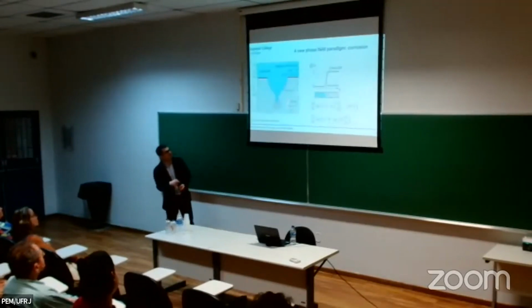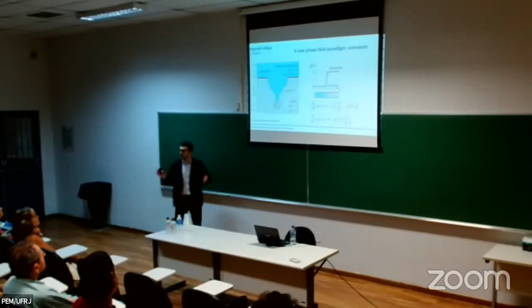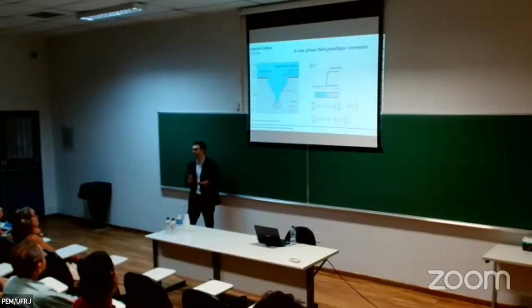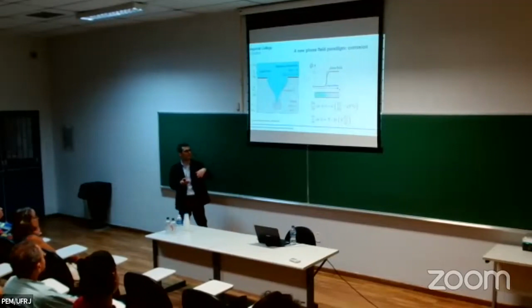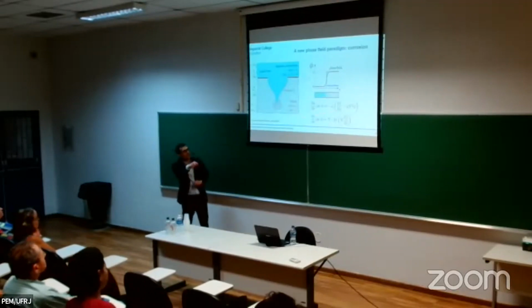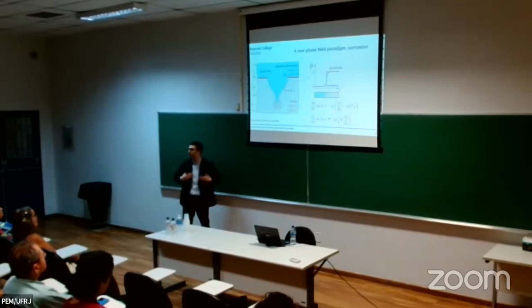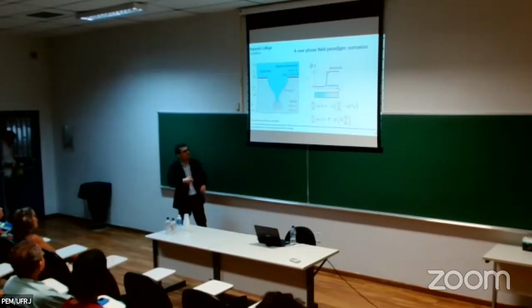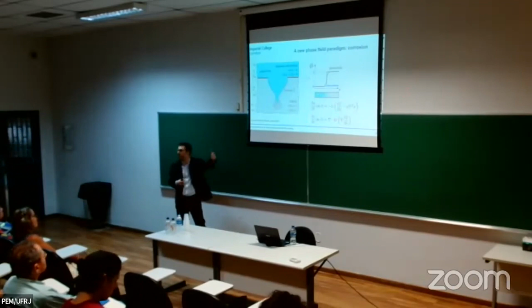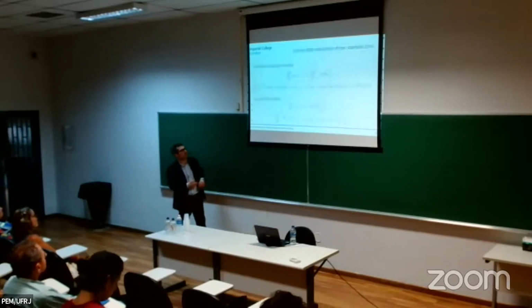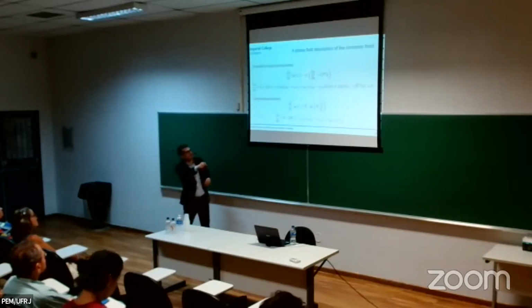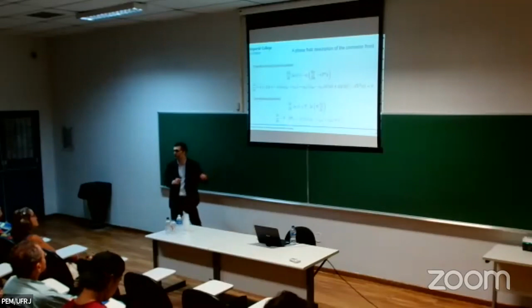We decided, okay, let's use phase field now to describe the interface between seawater and the metal. I won't get into the details for the sake of time, but these phase field models are similar to those used in microstructural evolution. So you have essentially the KKS model. You have basically two equations: one that describes the short-range interaction, the corrosion process itself, the dissolution of material, and another that describes the diffusion of metal ions away from the corrosion. Your model has two key parameters, the mobility coefficient of the phase field and the diffusion coefficient of the metal ions, and both we can relate to physics.